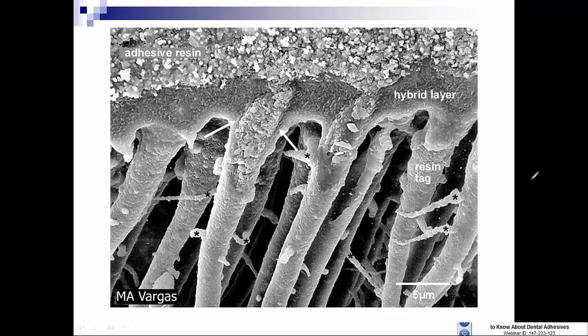Now, one principle we need to understand, and this goes back to this so-called invisible interface. The steps of bonding, regardless of using a self-etching adhesive or an etch-and-rinse adhesive, should be followed very carefully, because each and every time we bond, in particular to dentin, we create a new composition of matter. At the top of this scanning micrograph, we have the adhesive resin. In the middle, or thereabouts, we see a layer called the hybrid layer. This is a mixture of collagen, some residual mineral, and resin that was interpenetrated in and around the collagen fibrils.